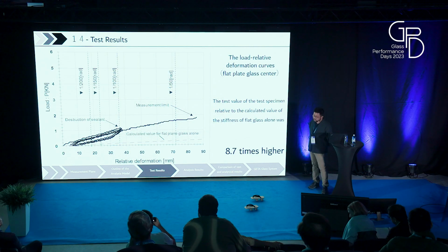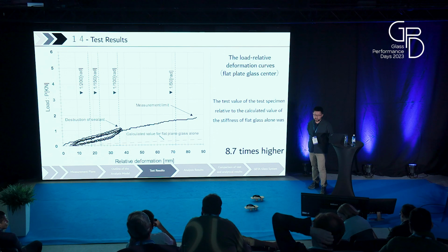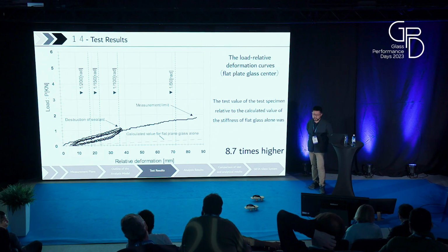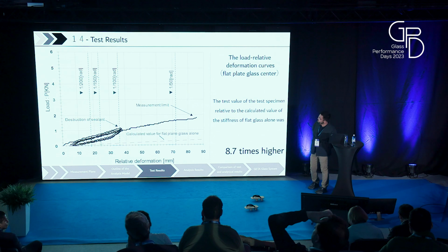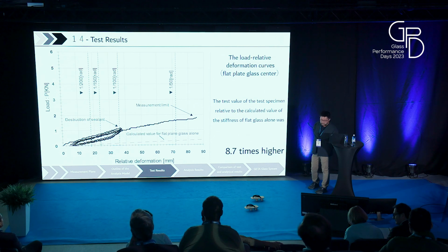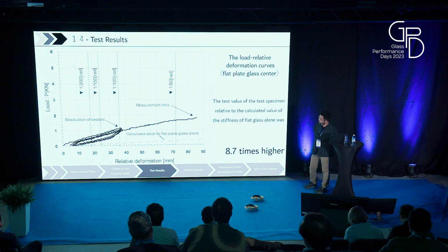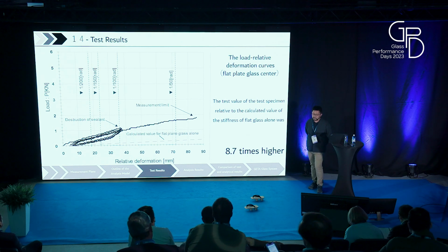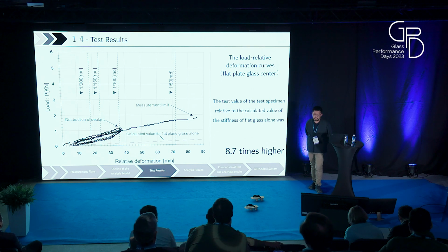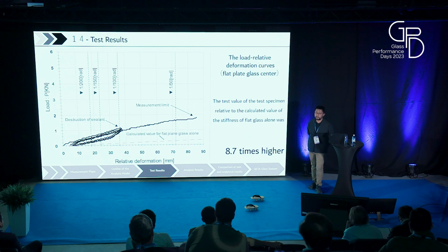Okay. And these are the load-deformation curves obtained from the bending tests. The vertical axis indicates the applied loads, and the horizontal axis indicates the relative deformation. And the test shows that the stiffness of the flat glass with the stiffeners was 8.7 times higher than that without stiffeners, which means a reinforcing effect was obtained by bonding the slender glass stiffener.